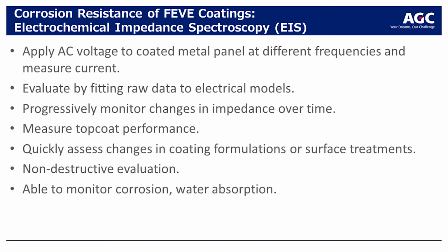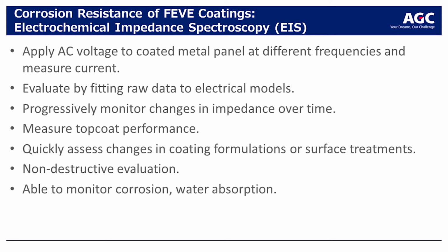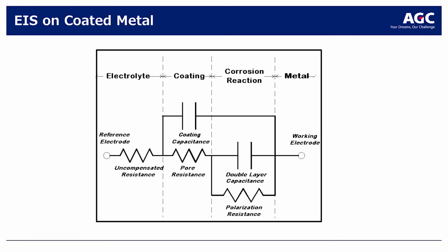It's also a non-destructive evaluation. In other words, you're not scratching or destroying the coating. You're looking at what the undamaged coating does to prevent corrosion. You can monitor corrosion, and you can also monitor things like water absorption in the coating. This is kind of what you're looking at. The electrolyte is the water or salt water you're exposing the coating to. There's going to be a corrosion reaction at the metal surface, and then you've got the metal itself. So it's a fairly complex thing that you're seeking to measure with EIS.